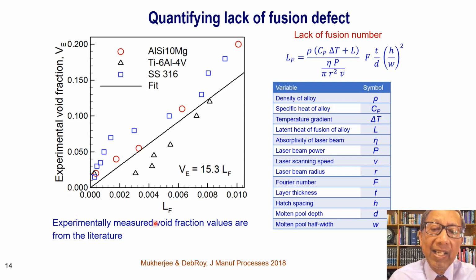When we plot the lack of fusion index or lack of fusion number on the x-axis versus independent experimental data on void fraction, we see a linear trend. So the model can be validated with independent experimental data, and the use of the model would require the values of the fusion zone dimensions, and these have to be obtained from a separate independent model.